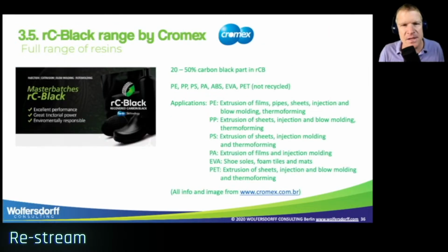Then we get the RC Black range by Cromex, and I really like this because it's the full range of resins. It is between 20 and 50% concentration of the carbon black part in the recovered carbon black. This is quite smart because keep in mind that in the recovered carbon black we have an ash content, and only the carbon black is a coloring component in the recovered carbon black.